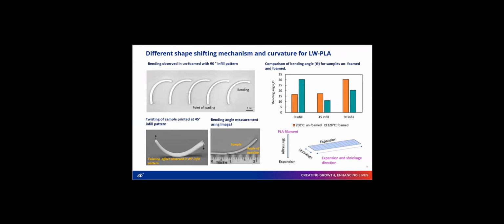Coming to the shape-shifting mechanism, we obtained bending for the samples printed at 0-degree and 90-degree infill patterns, and we obtained twisting for the samples printed at 45 degrees. This is consistent for both extrusion temperatures, for the foamed and unfoamed samples, and it is in line with the literature, due to the expansion and shrinkage of PLA.